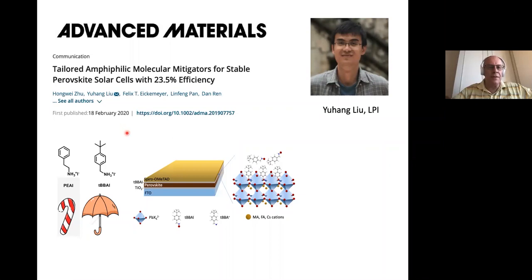And I just wanted to mention it, because normally people have used this phenylethyl ammonium iodide as a passivating molecule. The idea is that you take that to the perovskite surface between perovskite and spiro, and then you can passivate recombination centers to reduce losses. Maybe you can even extract the holes faster to the spiro.